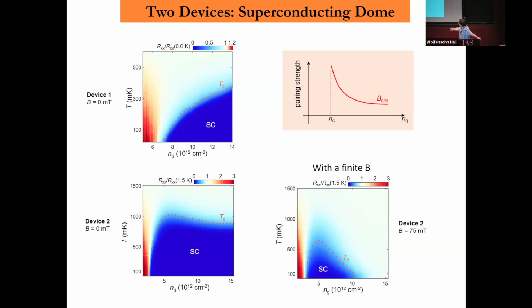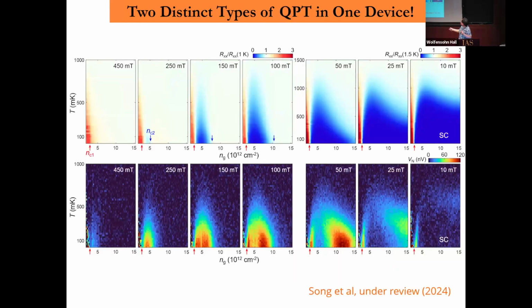What's amazing about this map is now you see two quantum critical points, two quantum phase transitions induced by density. One is going to lower density from the same superconducting state. The other, I increase the density, go higher. What's the difference? If I told you this one is special, is this also special? So there are two quantum critical points observed in a single device, and we want to contrast them. This is how we measure the data more comprehensively.